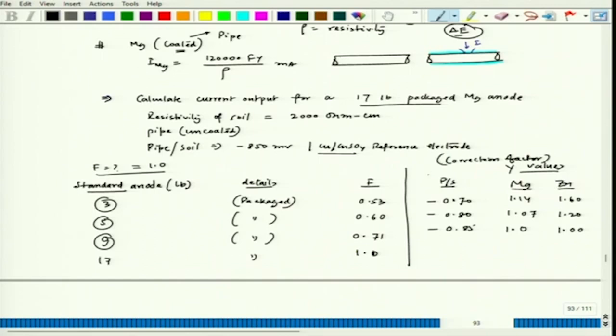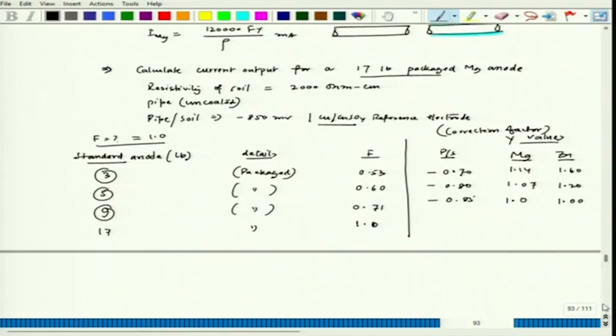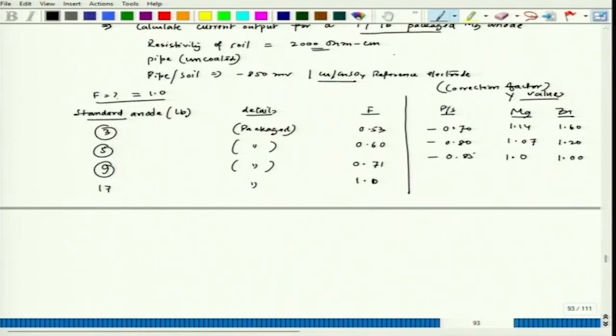So, this is Y, which is a correction factor actually, and it is dependent on the resistivity of the soil and also the dimension. So, this factor Y comes up, and we also know the resistivity. The resistivity value is already given, so you put those in that equation. Here, since it's bare, we have to use I_mg equal to 12000 F Y divided by rho. Now, since it's a packaged magnesium anode, F becomes Y.